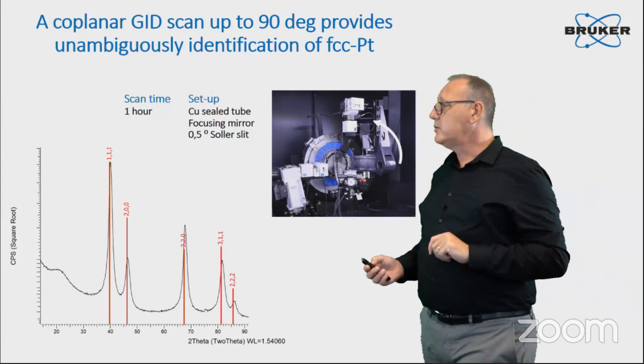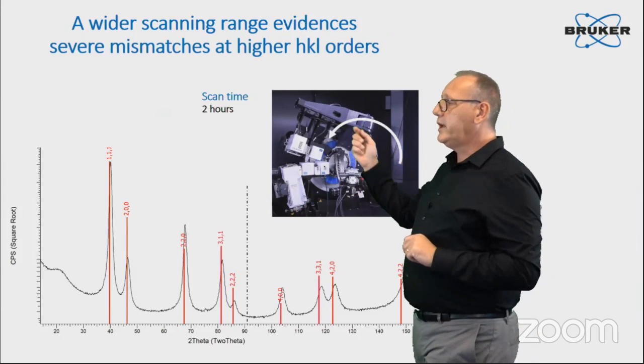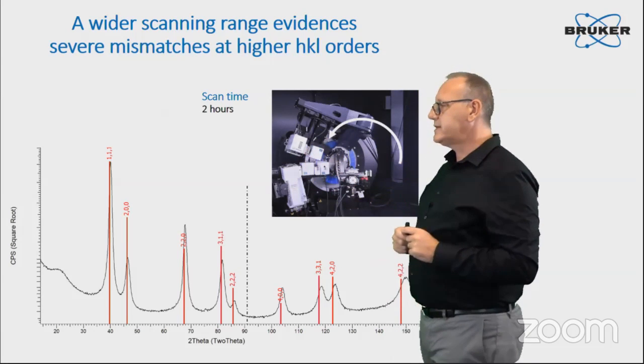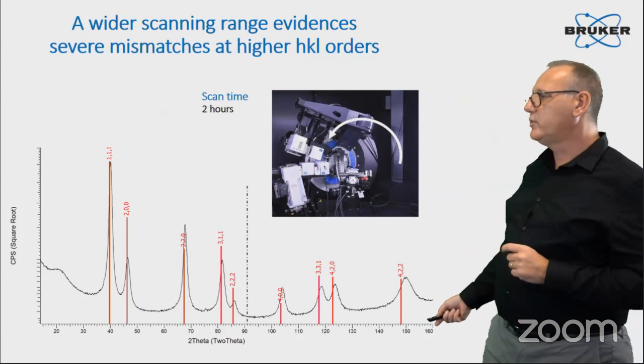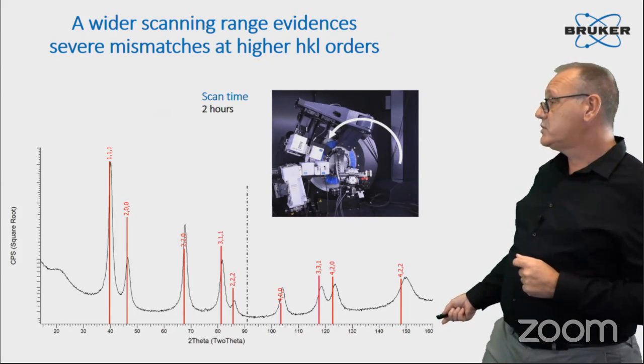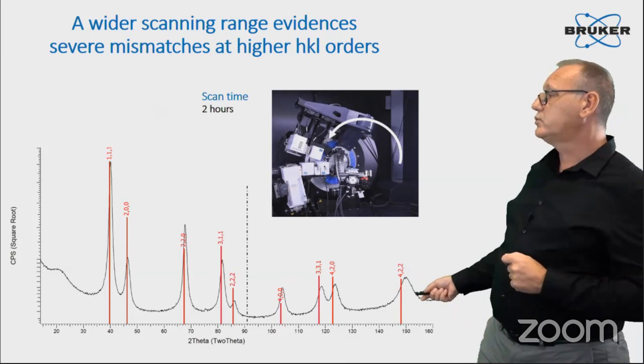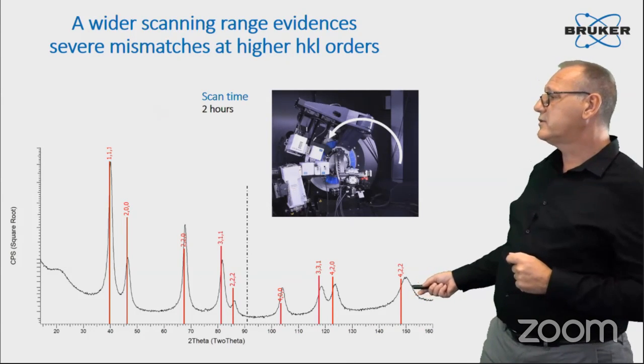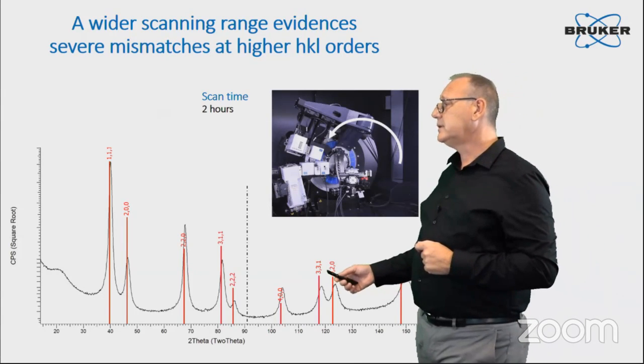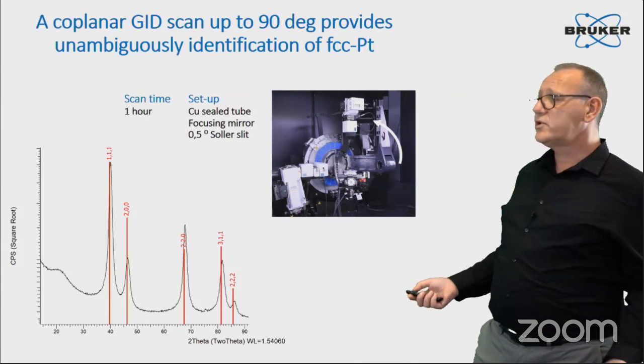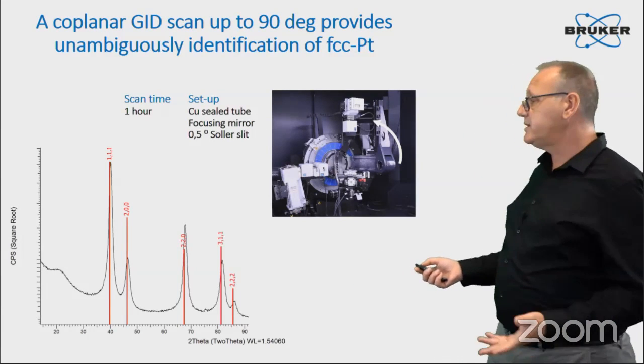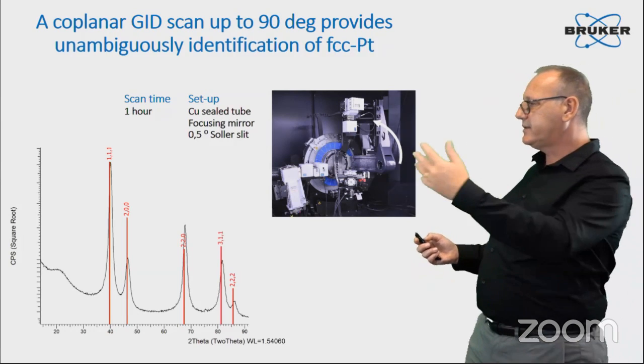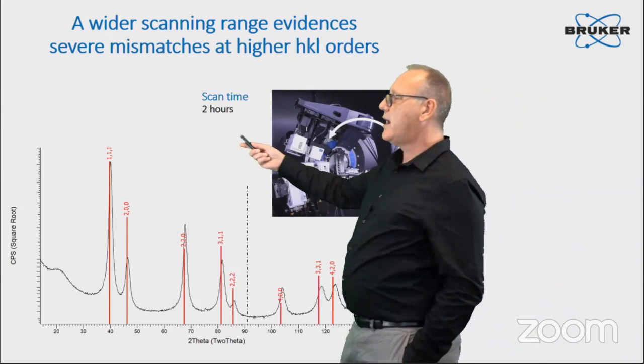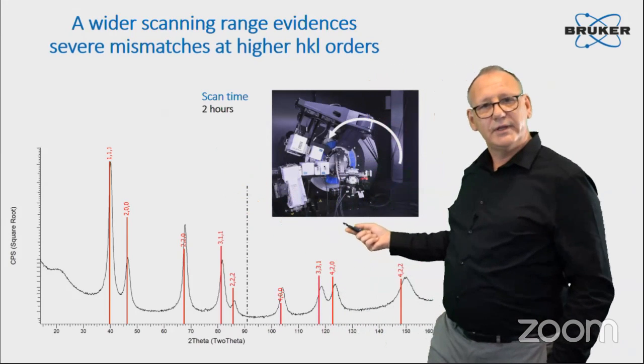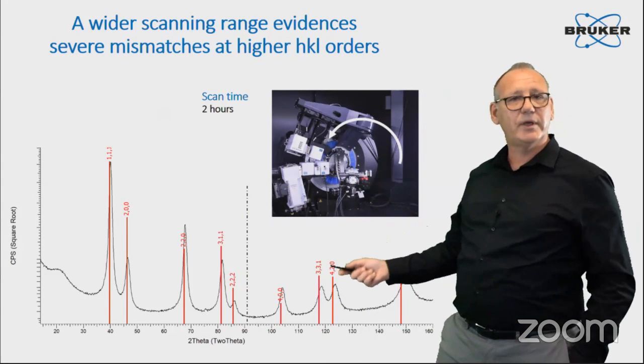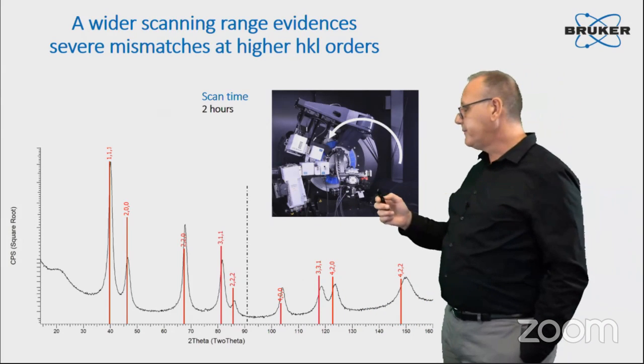But if you simply go a little bit further in your scan and go all the way up to the end of the scanning range accessible on that machine, and here we were actually able to measure up to 160 degrees, which is very good because we were also able to catch the 422 peak of platinum. What we observe is that we have a severe mismatch at high angle. So the situation we had before, while measuring only at 90 degrees, we think everything is nice in a perfect world. If we simply extend the scan, and this is only an additional hour, so instead of 1 hour, I measured 2 hours, it looks like this additional hour gave me a lot more information. We'll explain that in a moment.